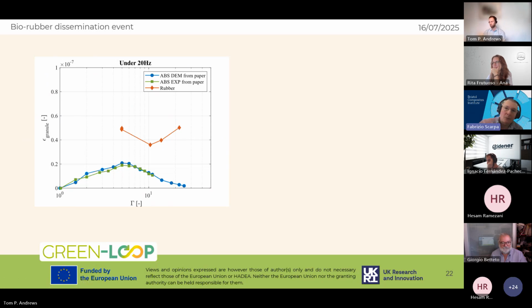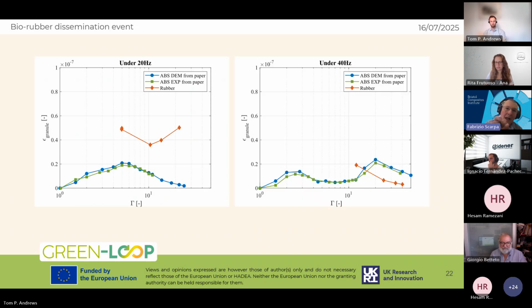In this slide, you see what happens when you excite the damper with a low frequency vibration. You can see the efficiency versus the normalized maximum excitation Gamma. Low frequency vibrations are among the most difficult ones to damp with normal types of materials. If you compare a classical particle damper made with ABS plastics and the one with the rubber, you will see that at low frequency vibration, the rubber provides a better elastic response, better fluidization, so you have a higher efficiency per unit weight because the rubber, even though it has the same volume fraction as the ABS, is lighter.